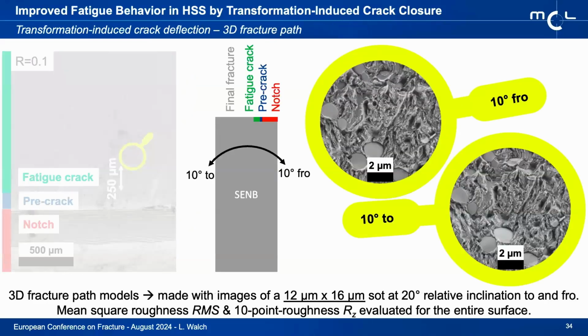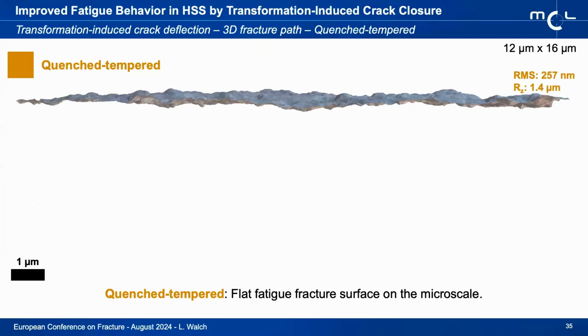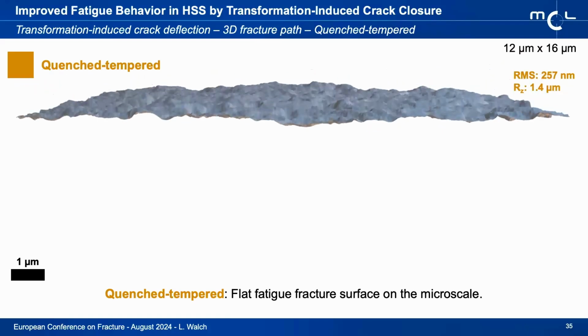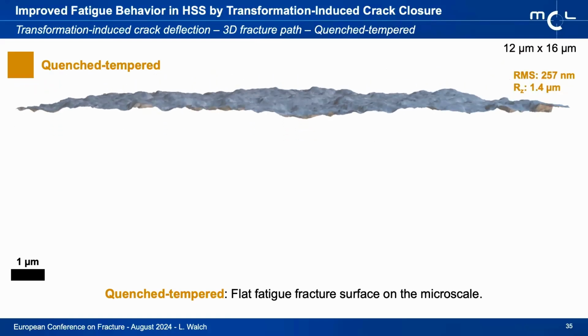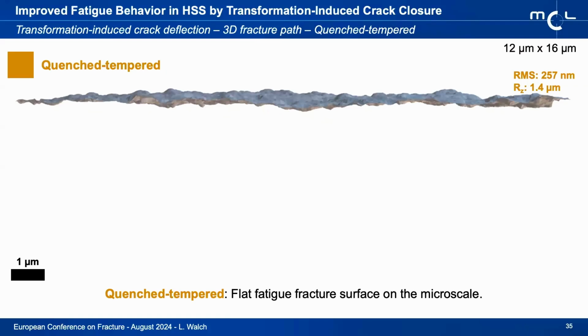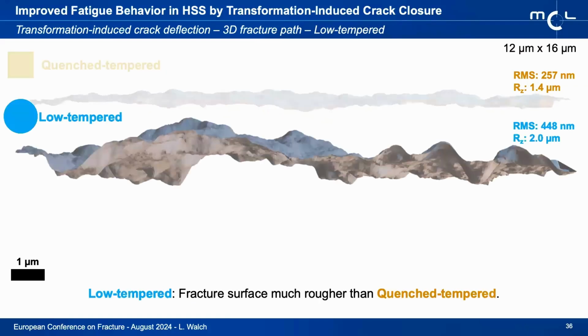First, I just looked at a very small localized part of the microstructure of each specimen, tilted at 20 degrees, fed it into photostereometric software, and got a 3D model of the fatigue fracture surface because it looks really nice. And here, also very flat. So that's our reference state. Seems that the crack propagates quite nicely in one plane.